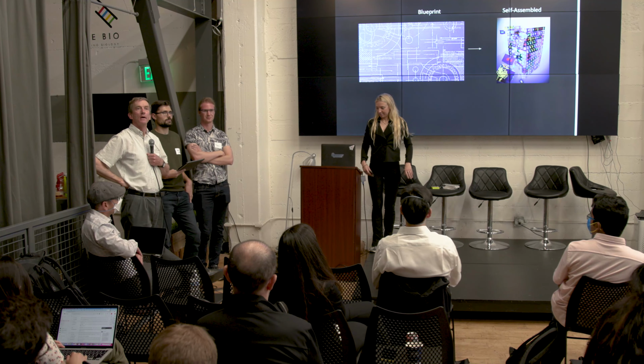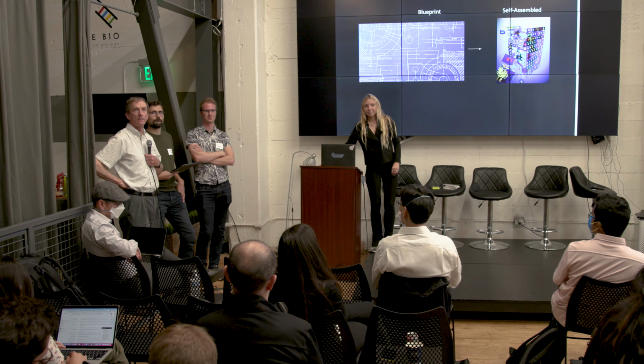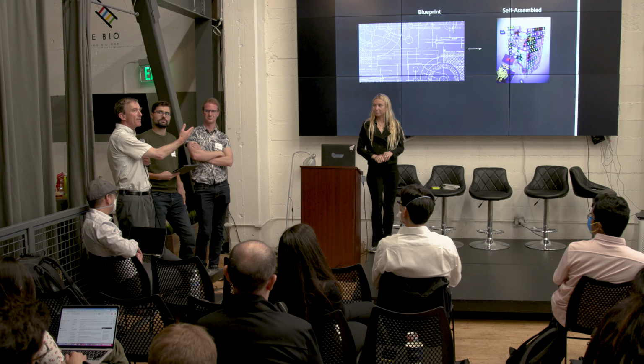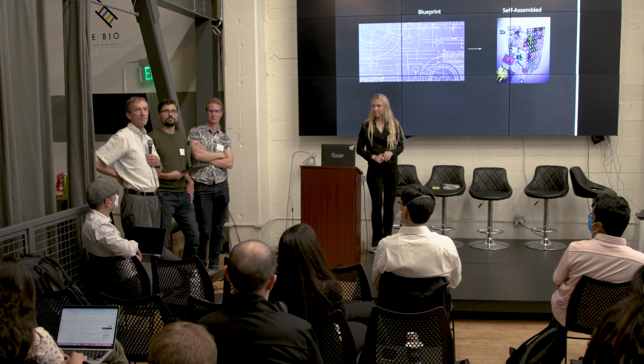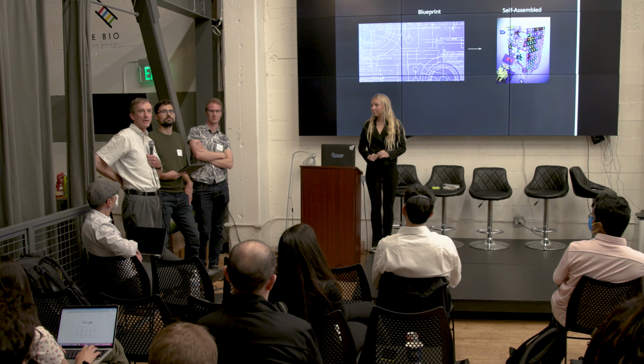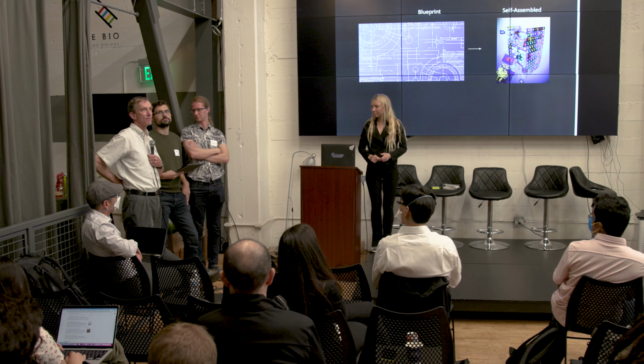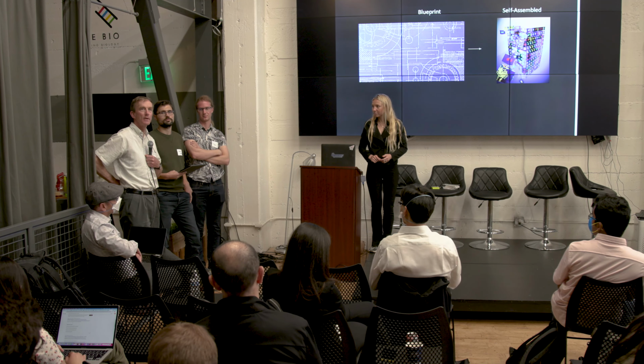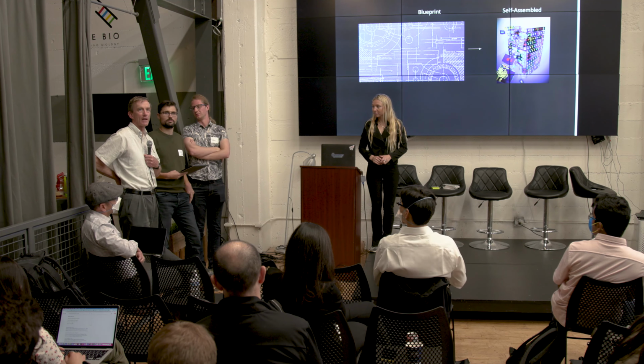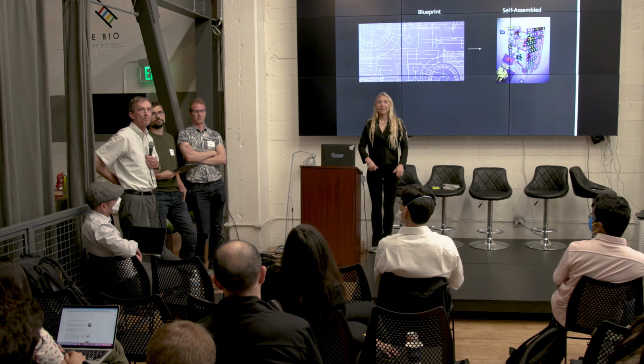Right. Which is why you might think about using nanotubes. The trouble with those is they're out of control in terms of length. They're very difficult to functionalize. But if you do the math, you can get maybe a 2-3 scale factor. I think we're talking about shooting for something of 2, 3, 5 initially. Okay. And I agree, to do something really useful, you probably need to go further, and that becomes a bit more of a challenge. But you've got to start somewhere. Cool, thanks.